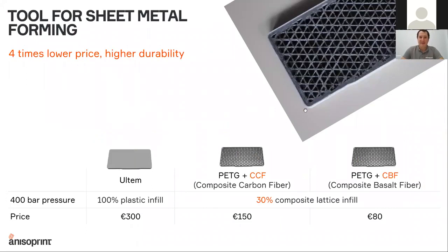This is an example of using lattices for tooling applications. This is actually a cold metal stamping die, the mold that has to carry a very high pressure load, more than 400 bar pressure, and if it's made just from plastic material with a 100% infill, it will not be able to carry that load. So that's the compression load in a transverse fiber direction. But with already 30% of the fiber infill, you can get a part that is much more durable and that can carry these high pressure loads.